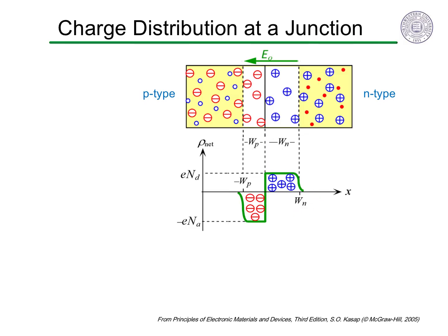Because the entire system was charge balanced to begin with, it should be charge balanced after the free charges diffuse. Here we see 5 negatively charged acceptor defects compensated by 5 donor defects, more spread out because the n-type side was more lightly doped. This gives us a relation for the relative widths of the two regions that depends on the dopant concentration. Thus, we can expect that lightly doped semiconductors have a wider depletion region than heavily doped semiconductors or metals.